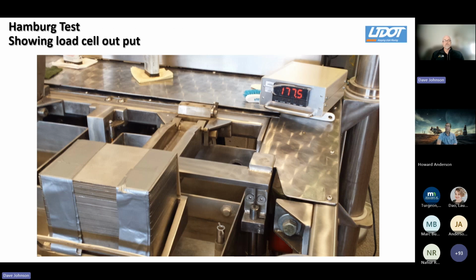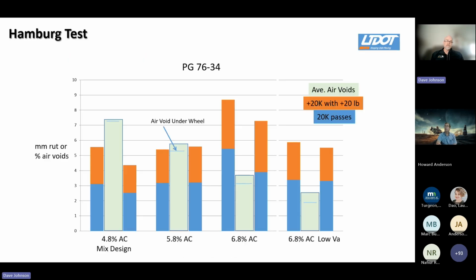I said that they made some changes to the Hamburg. You'll notice the duct tape extra weight. So they ran the Hamburg at its standard process for 20,000 cycles, and then they increased the weight for the second 20,000 cycles. You can see the results with, in the blue, the original 20,000 passes, and then in the orange, the additional 20,000 with the extra 20 pounds. So 158 pounds is your normal loading, and the second set was with 178 pounds.